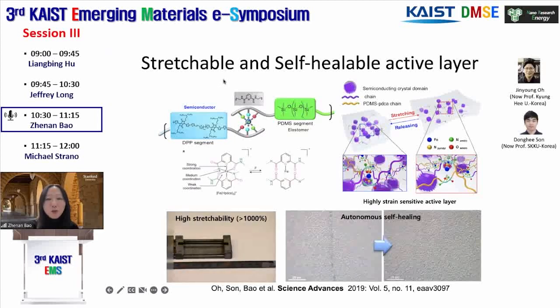And for self-healable and stretchable polymer semiconductors, we designed the suitable polymer semiconductor and its matrix so that it can also form the nanostructures that are needed. But in this case, having a dynamic polymer matrix allows these nanostructures to be carried across the damaged region. So originally, the semiconducting polymer itself is not dynamic, but the nanostructure embedded in the matrix is dynamic, and this leads to the healing of the semiconducting structure.